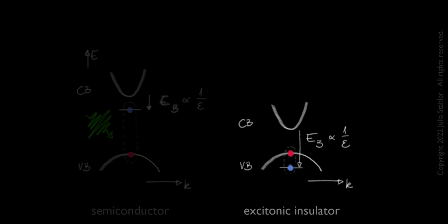Spontaneous exciton formation occurs in order to minimize the energy of the material. This happens by the formation of an exciton condensate. As a consequence, the bandgap widens compared to the semiconducting state and exhibits the characteristic flat top valence band. The material becomes an excitonic insulator.